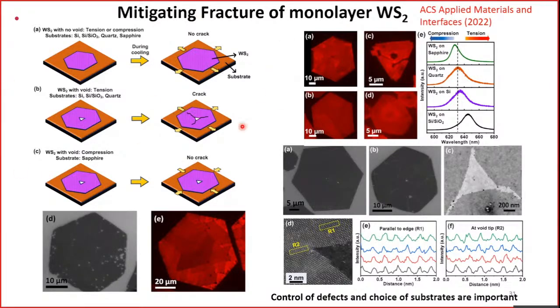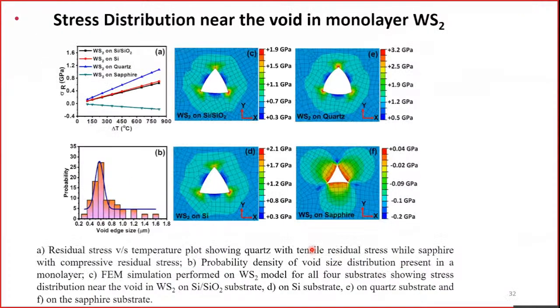So we have clearly looked at severe fracture in the case of Si/SiO2, and no fracture in the case of sapphire. Even if there is a void on a sapphire substrate, you would not see any cracking taking place. Again, we have looked at the microscope, right? We also did the basic FEM simulation, and also Abaqus and so on, to understand how the stress or strain is distributed around the void.